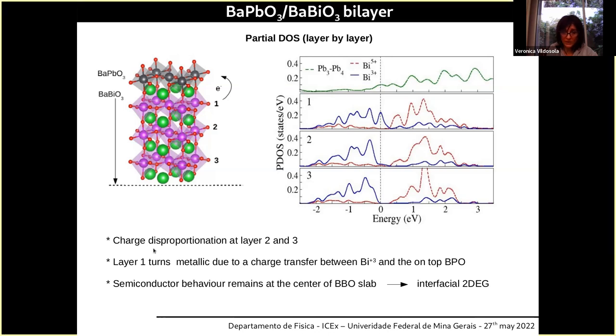So we observe the charge disproportionation at layers 2 and 3. Layer 1 turns metallic due to the charge transfer between bismuth 3+ and the on-top BPO layer. And the semiconductor behavior remains at the center of the slab. So we can show that we have an interfacial two-dimensional electron gas in this material.